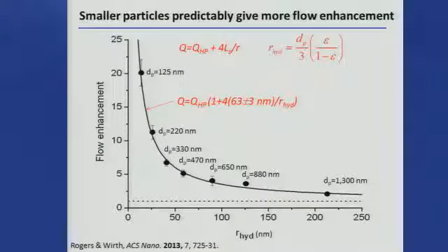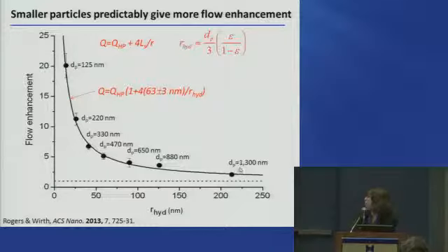And here are some data to help illustrate that. So my student Ben Rogers, who was very energetic, took a whole bunch of different particle sizes from this 1300 that I showed you earlier all the way down to, this is something like 122 plus or minus 2, so we sometimes call it 120, sometimes 125. The error bars are from 3 different capillaries. So he made 3 capillaries for each of these and then measured multiple flow rates. So multiple pressure versus flow curves had about 5 points. So many points went on to this.